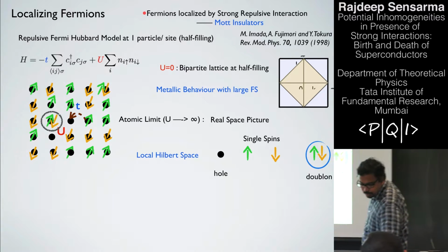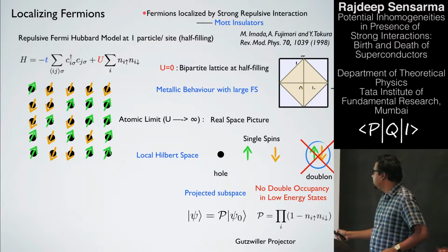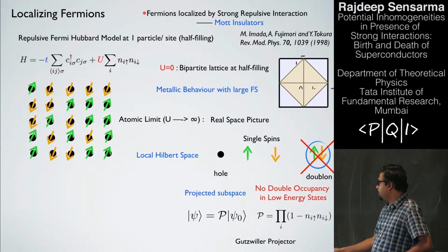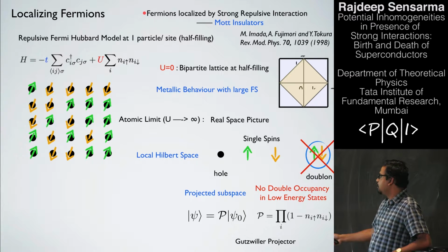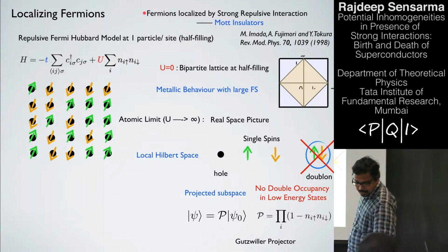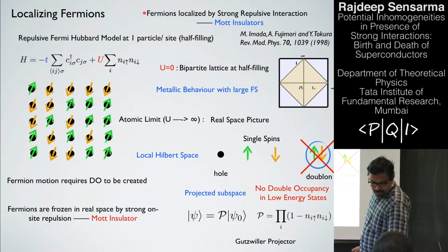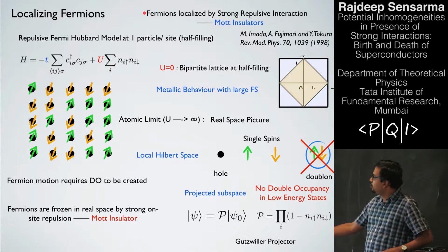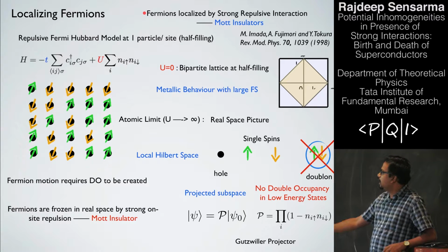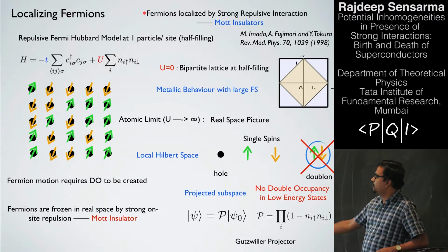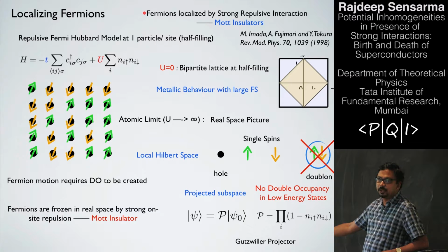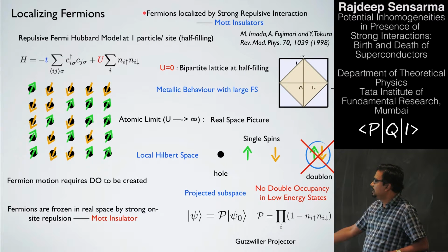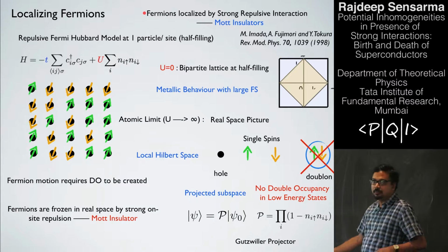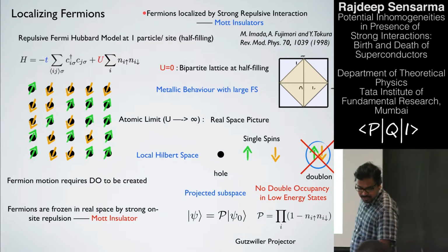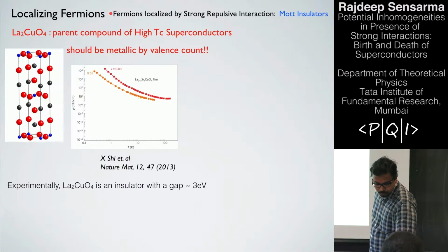And if U is large, you would say that, okay, these states are not allowed. So you should go into some kind of a projected subspace where there is no double occupancy in the low energy states. Now you can see, if there are no double occupancies and you have exactly one particle per site, you cannot move, because to move you have to create a double occupancy. You try to move anything, you will put two of them on the same site. So these are frozen in real space because you cannot access these high energy states. This is called a Mott insulator.